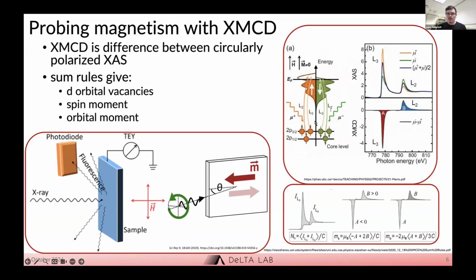So here, the electronic density of states that's associated with the 3D orbitals may favor a specific spin direction. So when we do circular left and circular right polarization in XAS, one of the spin directions might be favored, and we might see more absorption corresponding to that polarization, which then allows us to extract the magnetic properties of a material through the spin anisotropy.